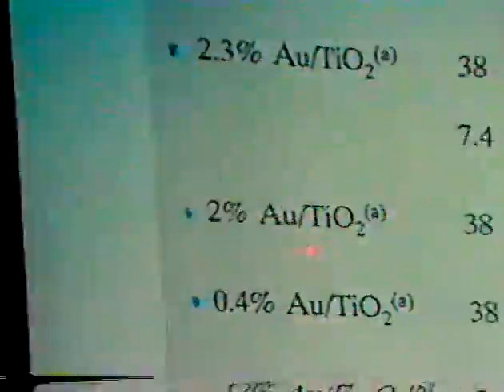And from our X-ray diffraction data and other TEM values, we know we have large gold particles. They are close to 300 angstroms. If we take these values and estimate turnover frequencies, our catalysts are at least as good as, and substantially more active than, the best catalysts that have been reported in the literature. We found recently in an obscure meeting in Europe that we just became aware of that they had reported also gold and titania. This is not in the open literature, but that catalyst was quite active. And again, taking the data from their paper, they had about 100 angstrom particles. We can estimate a turnover frequency and an activity per gold that is really quite comparable to the values that we had measured in our system.